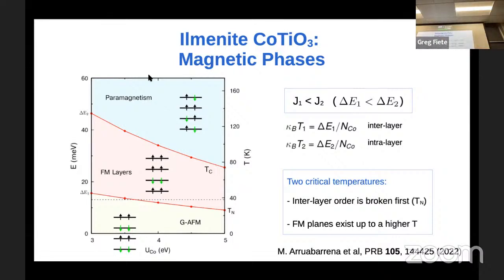At first, at low temperature, we will be in the GAFM state. At the Néel temperature, we will break this interlayer ordering so that we are no longer in this state, but in plane, we will still have the presence of ferromagnetic planes, even at temperatures that are higher than the Néel temperature. So therefore, we can tell that there are two critical temperatures in this compound, and that even above the Néel temperature, there might be some magnetic properties in the layers of cobalt, which would be of interest in 2 dimensions, for example.